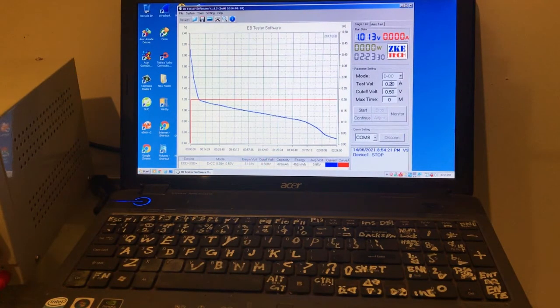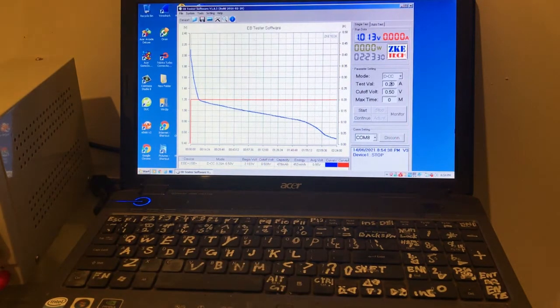Okay, so at 200 milliamp load, the cell runs for 2 hours and 23 minutes, which is 478 milliamp hours and 452 milliwatt hours. But the voltage is higher on its recovery. It normally sits around 0.9.